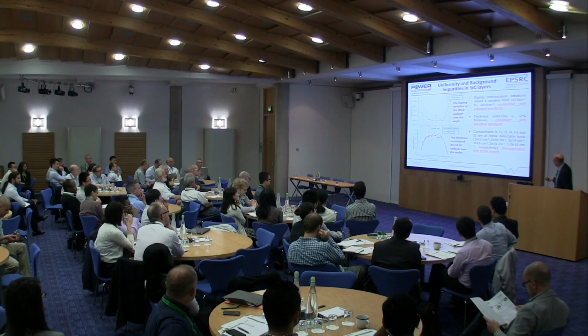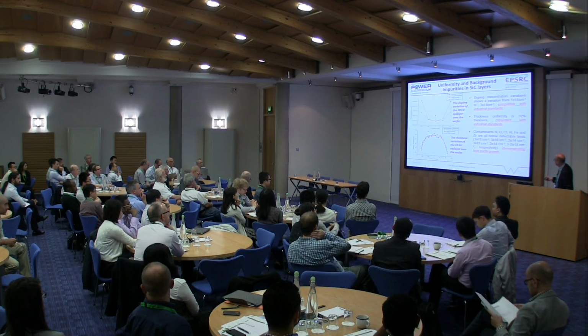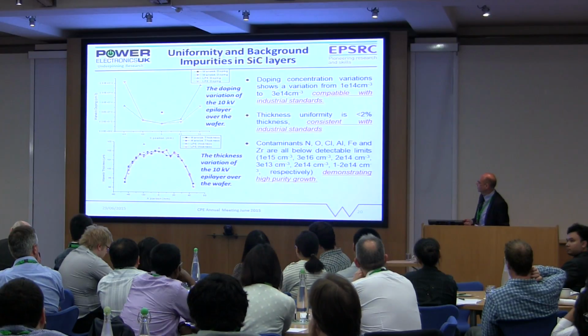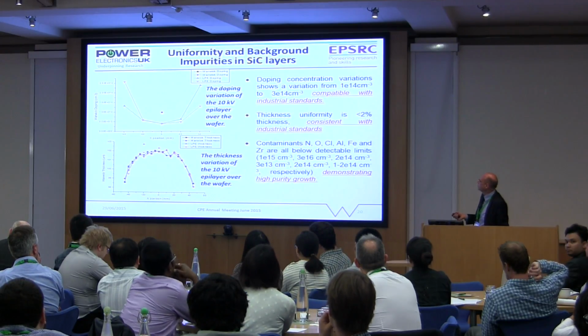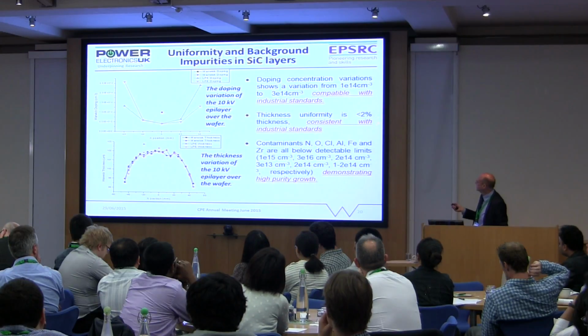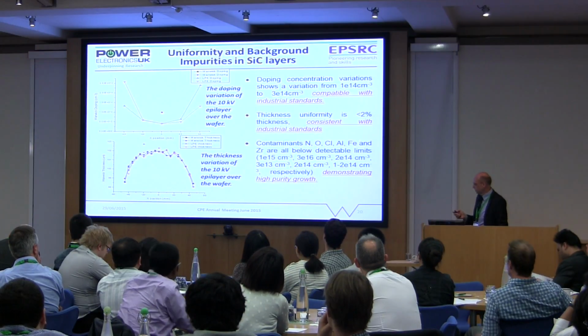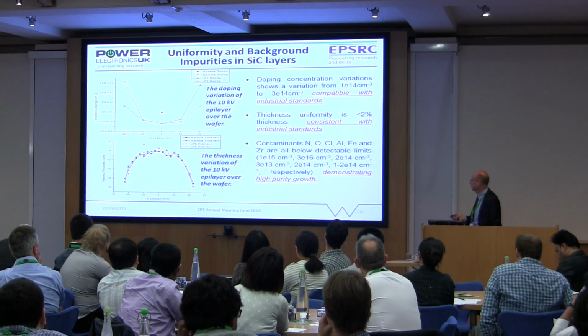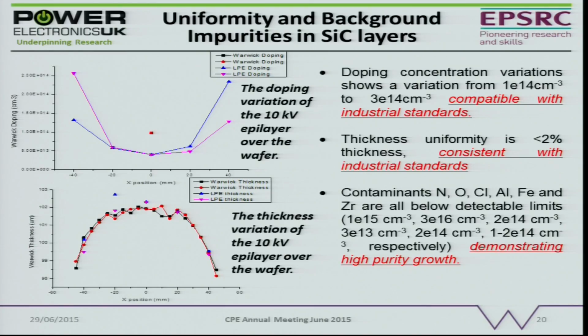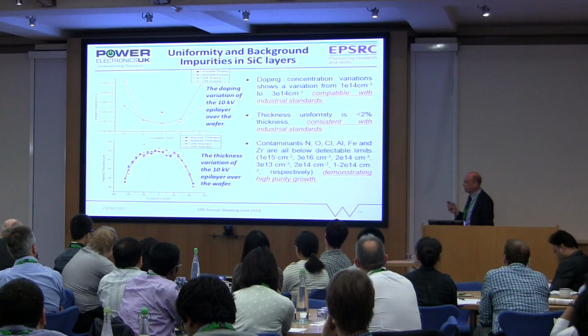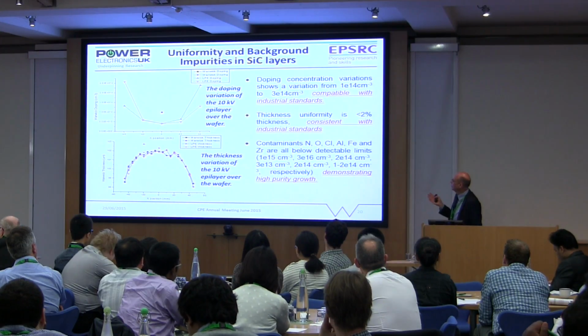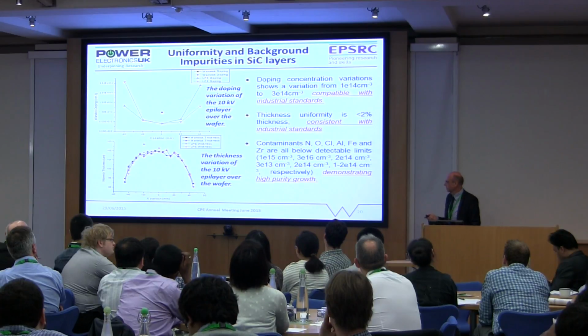The thickness of the wafer is pretty much identical to what the suppliers of the equipment can grow as well. So we found that the thickness is less than 2% across the wafer, which is what you can buy commercially. And we also found that there were small amounts of contaminants, but they were pretty much below the detectable limits. And so we demonstrated that the growth process was very high purity. So at that point, we've now got a system where we know we can grow high quality epitaxial layers.